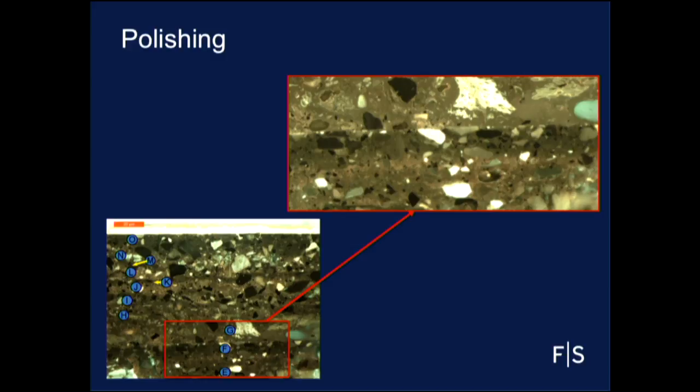But the more I look at it, the more I think that it's really evidence of the fact that they're using a very thick and viscous lacquer paste as they form this. And this is the only instance where it's not viscous, because if you're using a putty, you're going to have a much rougher surface because it will not be viscous enough to level and be flat and uniform. If it's a thinner lacquer layer, you would expect some leveling and a much more even interface. Of course, there is still evidence of polishing here.